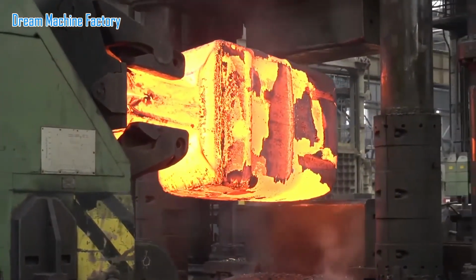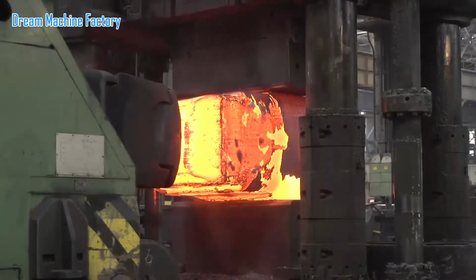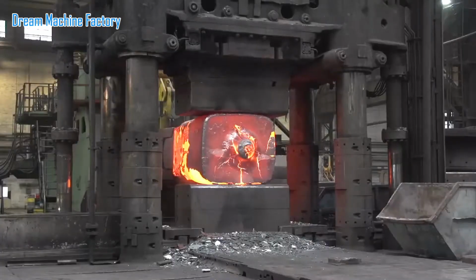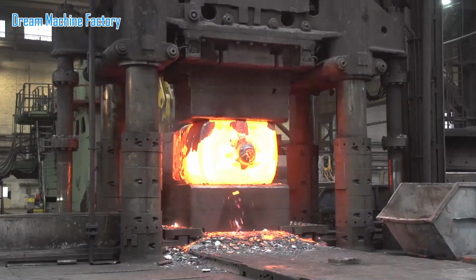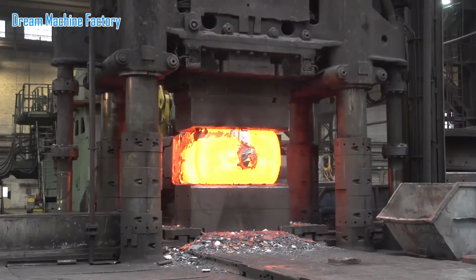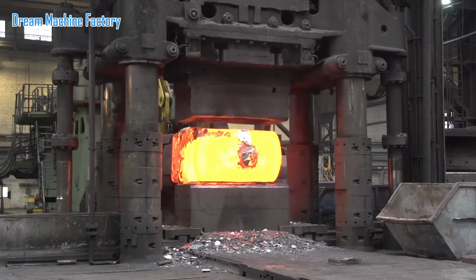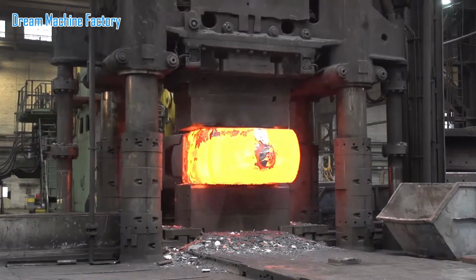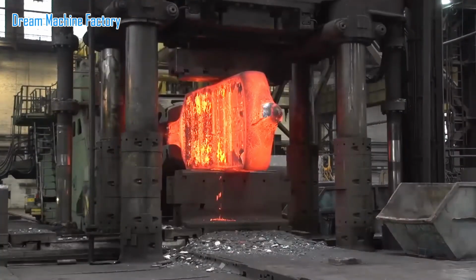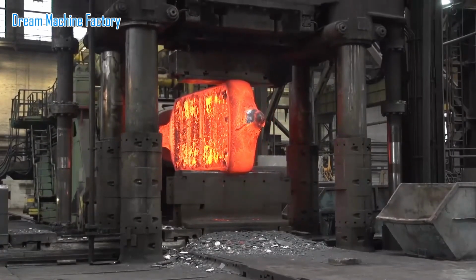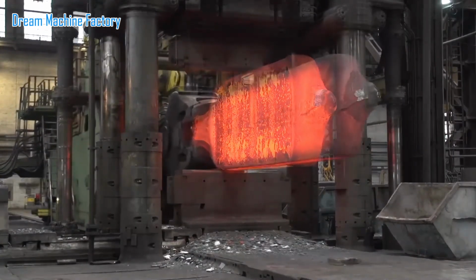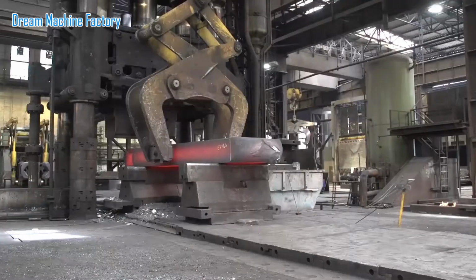During forging, the ingot is heated to a specific temperature and placed under the press, which applies massive pressure to refine the grain structure, eliminate internal voids, and improve mechanical properties. This process aligns the grain flow with the shape of the bar, enhancing strength, toughness, and fatigue resistance. The 60 meganewtons press is essential for producing high-quality forged steel bars.